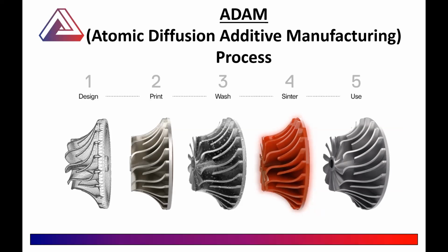When it comes out of the wash cycle, we re-weigh it, and we're looking for a percentage difference in weight. Once we hit that target, we're ready to move it on to the next process, which is the sintering process. The sinter is loaded up using an argon mix. It goes through a cycle, which is usually in the region of around 26 hours. Then the component is brought out and it's really ready for use, subject to any additional machining that you may require, any coatings, heat treatment, painting, etc. You can basically treat it like any other metal print after that process.